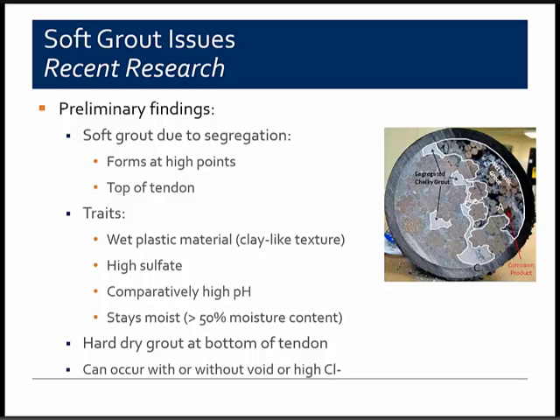Instead, the soft grout material forms, and it exhibits a tendency to stay in this wet plastic state, kind of resembling modeling clay, as Brian discussed, and the material stays wet or moist, much higher moisture content than the grout normally would exhibit. It also exhibits a different chemistry than the dry, harder grout that consolidates at the bottom of the duct, and that includes much higher sulfate content and high pH, particularly in the interstices between the wires where the oxygen availability is really low.